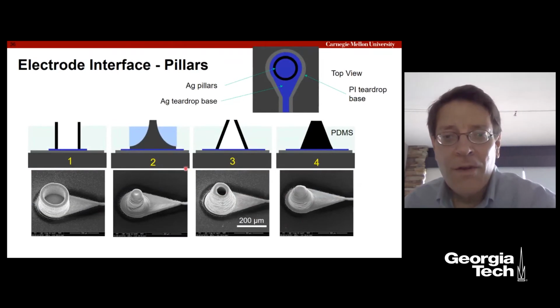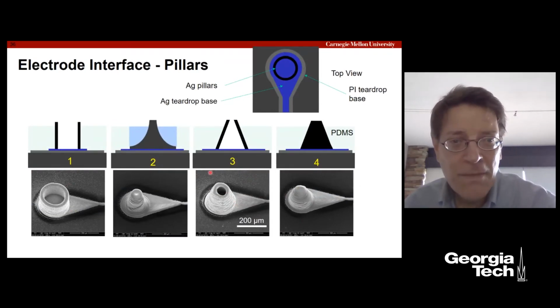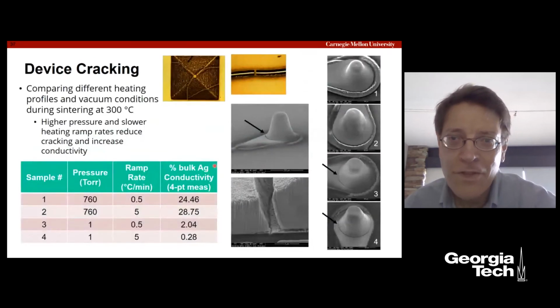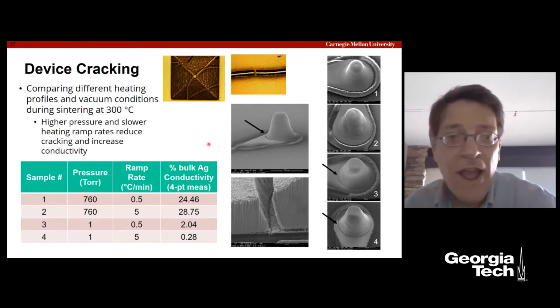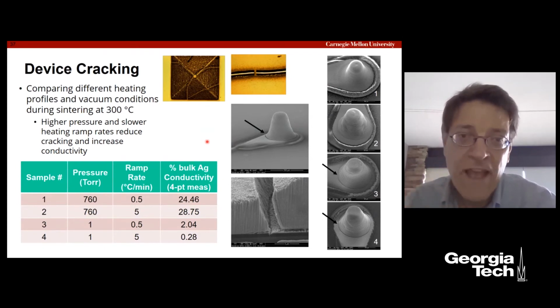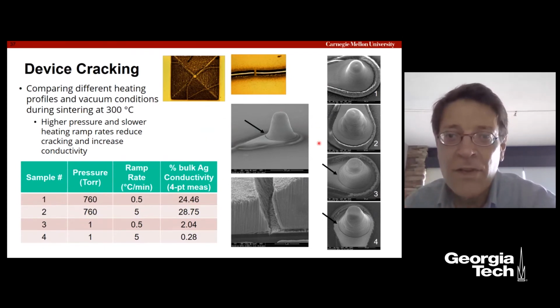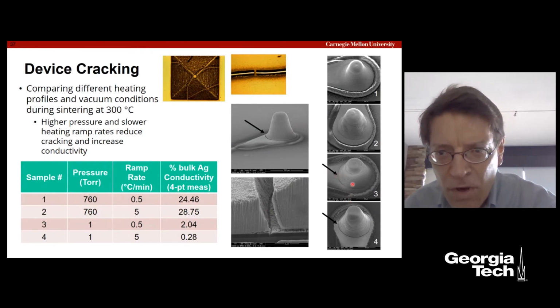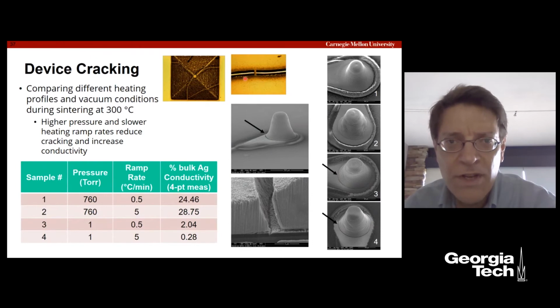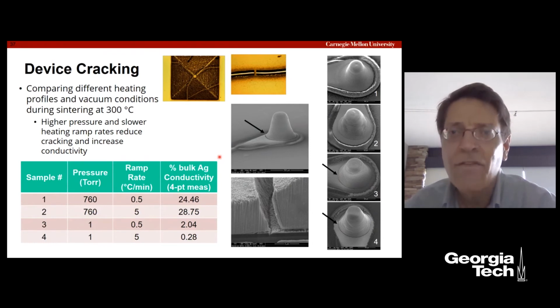So we made pillars. You can see here we talked about the pillars already, and so the third problem we had was cracking. And for the cracking, the issue has to do with fast evaporation. I'll get to that in a second. But you can see when we were making these devices and putting them in vacuum, we were getting these small cracks, but very distinct cracks around the pillars. Early in our studies, we also noticed we were getting cracks in wires and other features that we were aerosol jetting, and didn't really understand exactly how to avoid that.